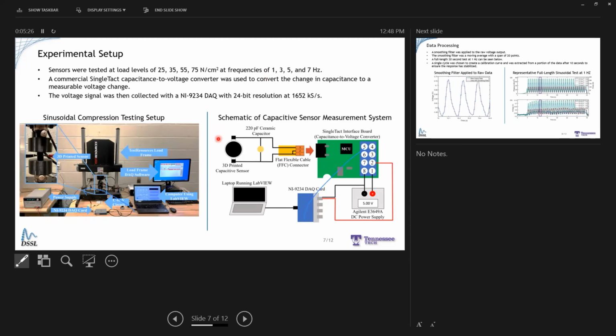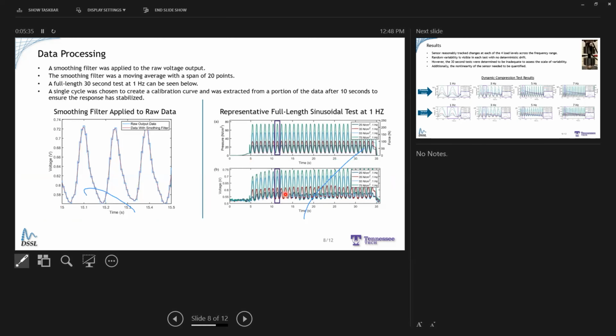In order to capture the signal, we used a capacitance to voltage converting circuit from SingleTact and an NI DAQ card running LabVIEW. Once we captured the signal, we smoothed the curves using a moving average filter. For each of the tests, we ran a 30-second test for each of the load levels and frequencies. We knew we wanted to assess the nonlinearity and get a calibration curve, so we extracted a single peak after the signal had stabilized to look at the calibration curve.